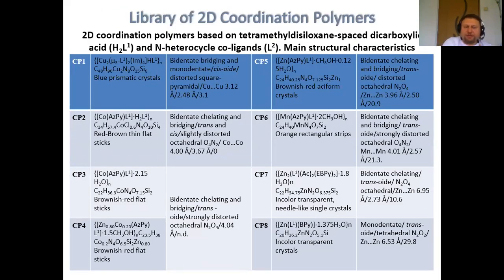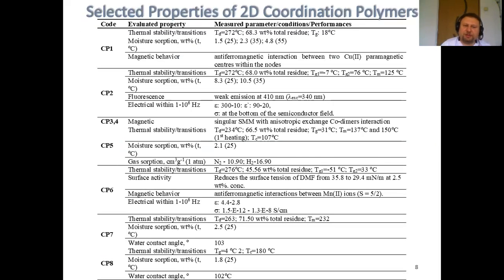An entire library of two-dimensional coordination polymers was synthesized as single crystals using the tetramethyl disiloxane spaced dicarboxylic acid and nitrogen heterocycle coligands by diversifying the permethylated component by the synthesis of new carboxylic compounds to contain it or by locating it in the core ligand. These coordination polymers were further characterized in terms of thermal properties, magnetic behavior, water vapor sorption, and gas sorption capability.